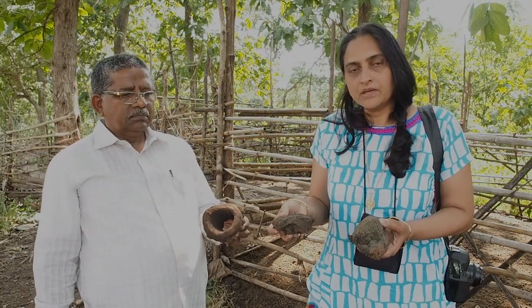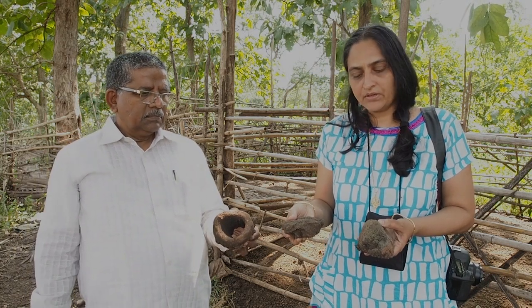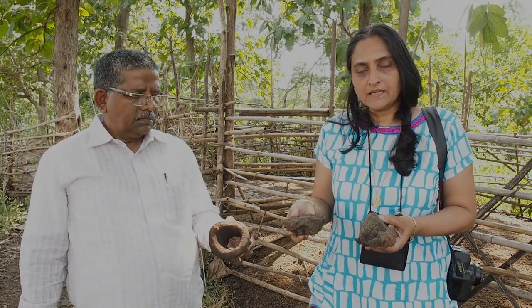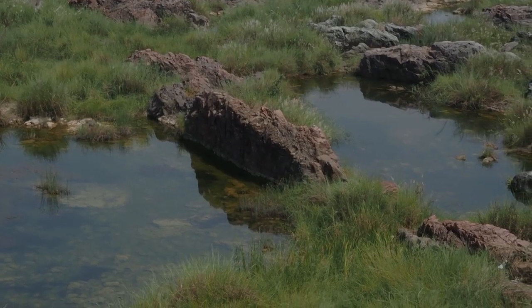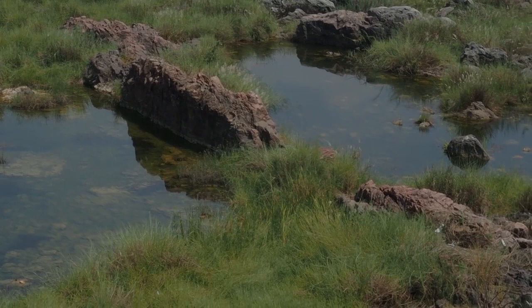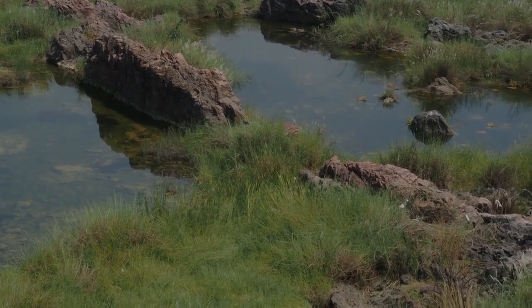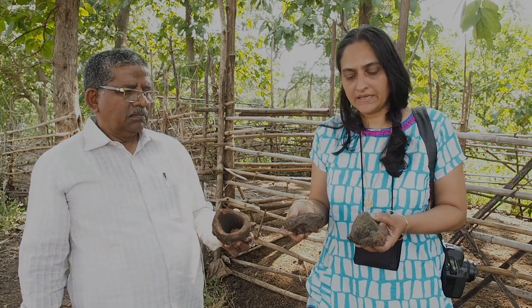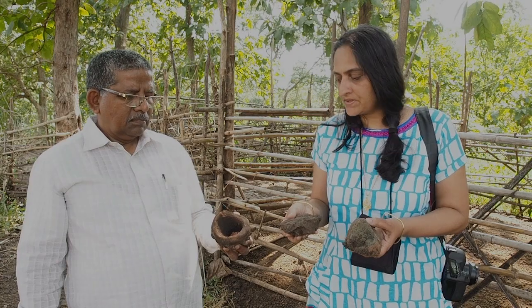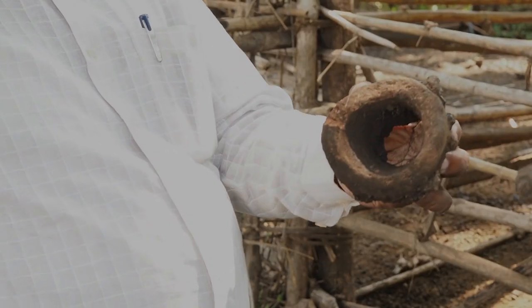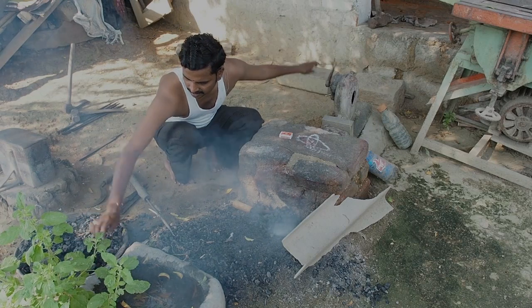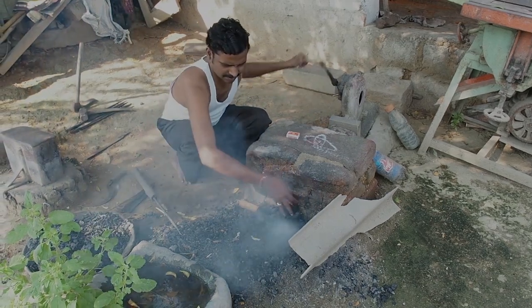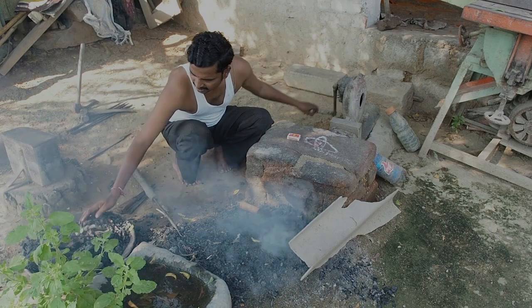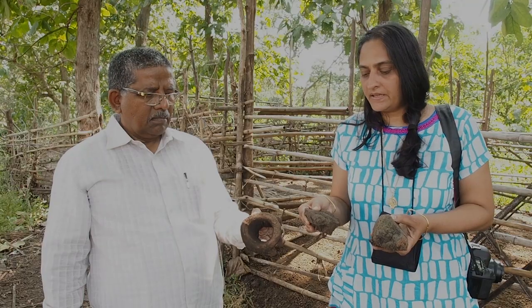So here, in fact, what has been going on is the smelting of bloomery iron, whereby iron ore has been collected from the river and smelted or reduced at high temperatures to form the solid iron bloom. And we are looking at the debris or waste products from the smelting of the iron blooms by the bloomery iron process. This is a tuyere, which is a blowpipe, used to blow wind into the furnace, a sort of draft into the furnace for the smelting process to reduce the iron ore.